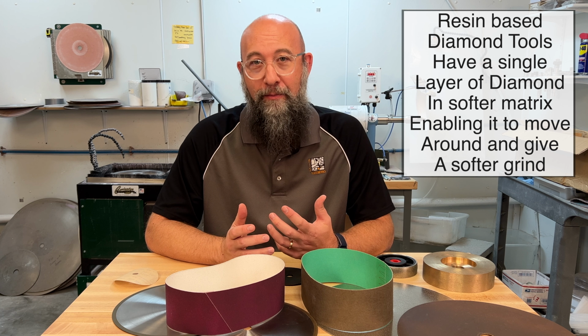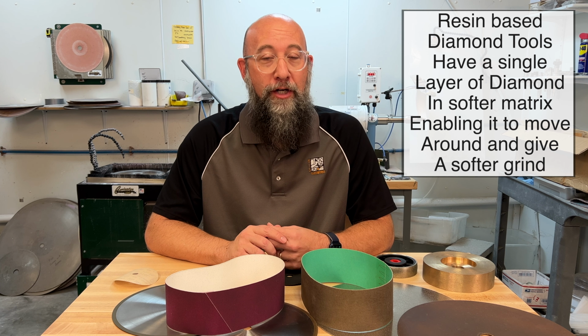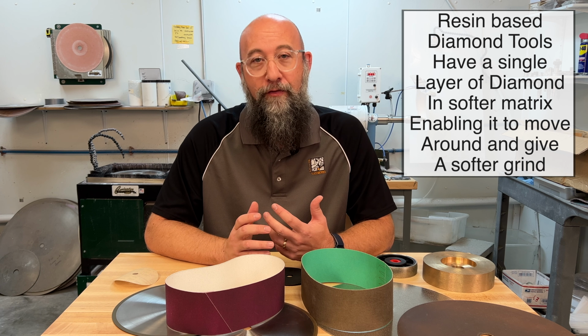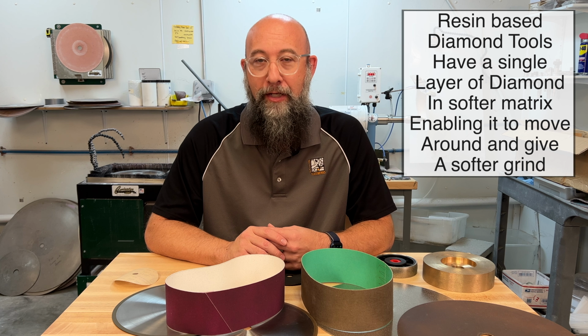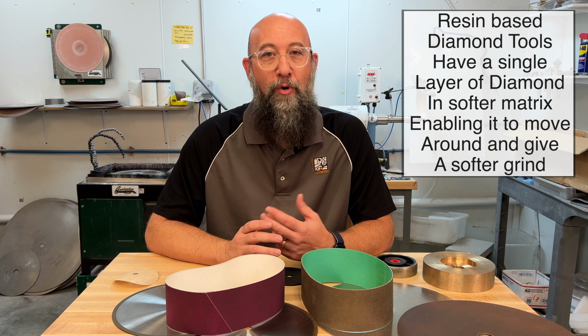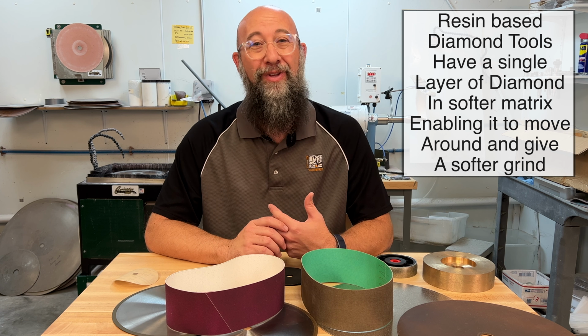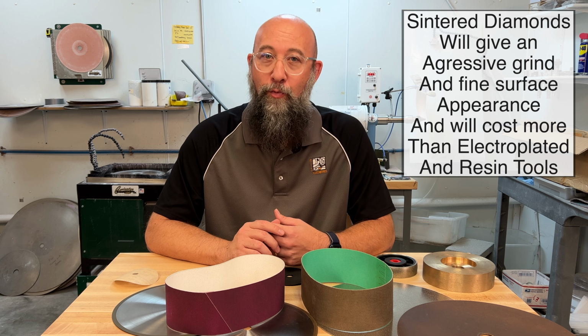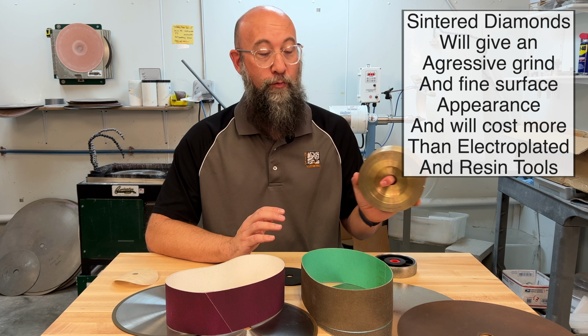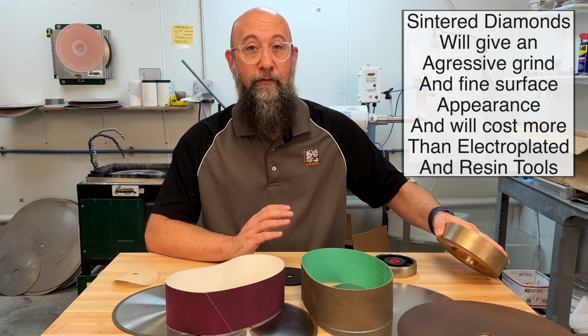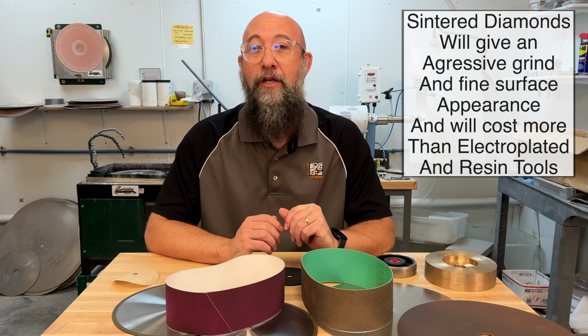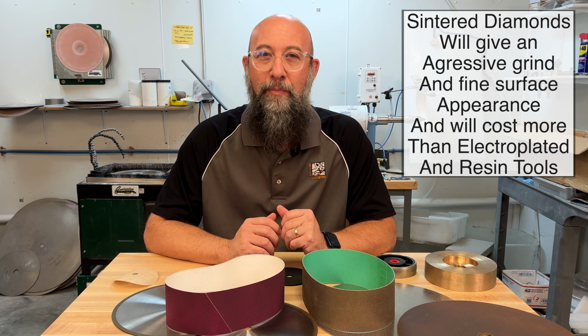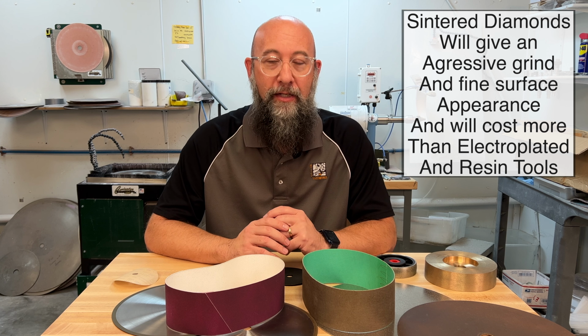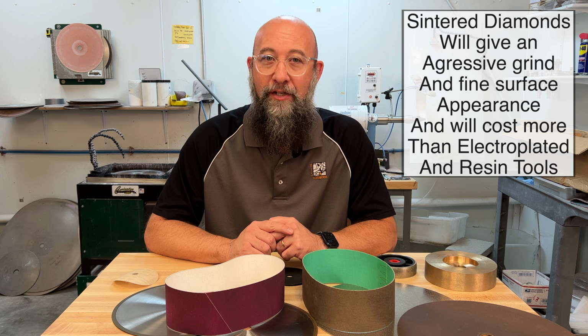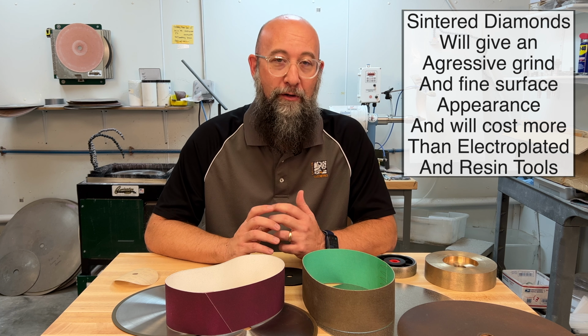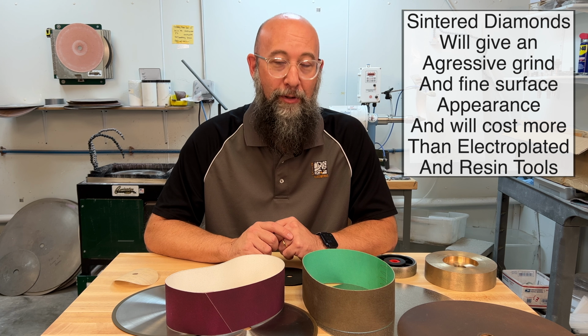With resin-based diamond tools, you have a single layer of diamond on there trapped into a resin, so it's in a softer matrix than if it were electroplated with nickel. That means it's going to move around a little bit more and give you a softer grind on the glass with less removal. Sintered diamonds, where they're mixed into a metal matrix, like this wheel or your saw blades, are going to give you an aggressive grind on the glass, but a fine surface appearance. So you kind of get the best of both worlds between electroplated and resin. Now, sintered diamond tools are going to be a lot more expensive, but in the long run, they will give you faster, better surfaces than electroplated or resin tools typically will.